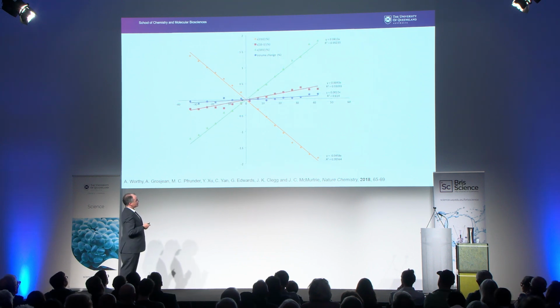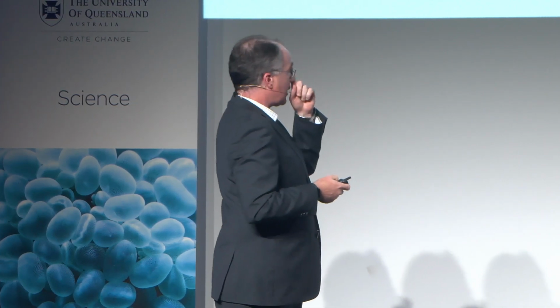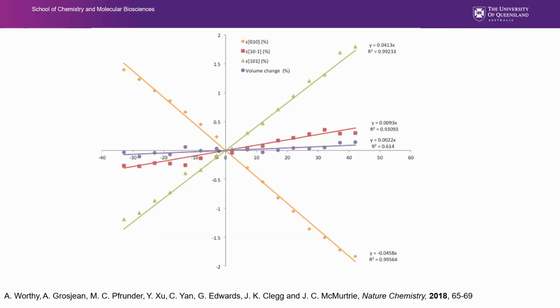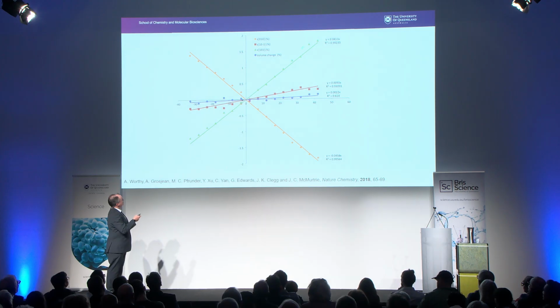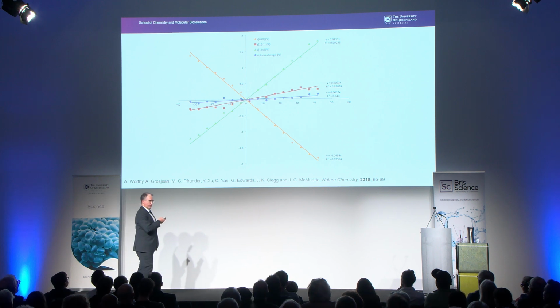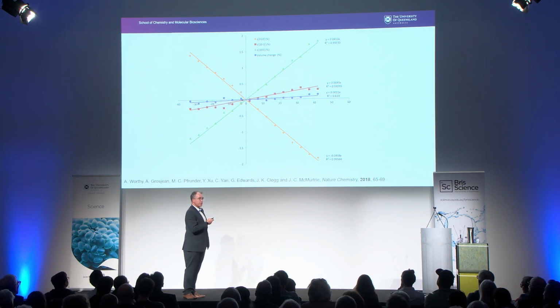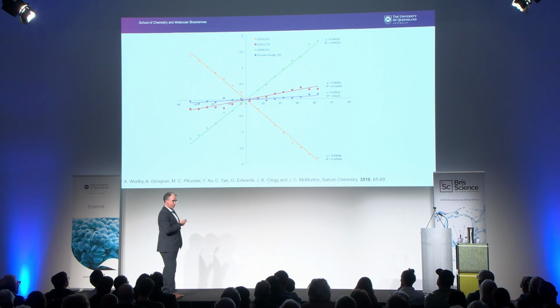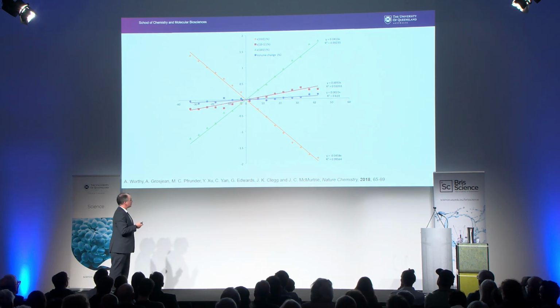When we have this crystal structure data, we can then plot this out in the size of the crystal itself, not just in the change in the unit cell axes, but we see exactly the same thing. So from the outside to the inside, we see the crystal going from long to short as we move from the outside to the inside of a bent crystal. We see an increase in the other direction, in the A and the C axes, but also quite interestingly, we see no real change in volume. And that's important from a physics perspective because it says we're not really doing much work when we're bending the crystal. We're putting energy in, but we're not really changing it to anything else.